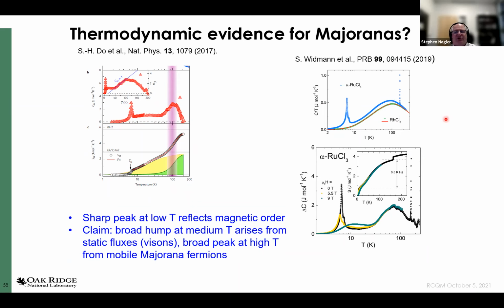A German group, Widmann et al., measured the specific heat fairly carefully, and they did it in a field of 9 Tesla, which is enough to kill the order. Very interestingly, they see this double hump feature, which, if you believe this could be related to a Kitaev quantum spin liquid, might be the signature of, on the one hand, the visons or static fluxes, and on the other hand, the Majorana fermions. In any case, it looks that way, and that has whetted people's appetites for thinking maybe you have Majoranas here, with some thermodynamic evidence for them.